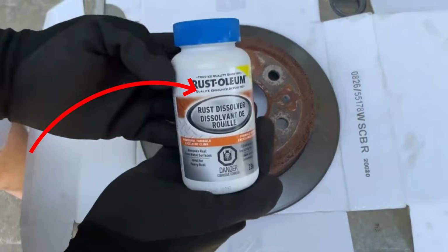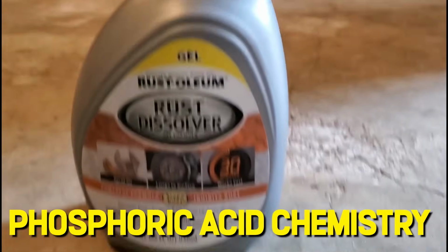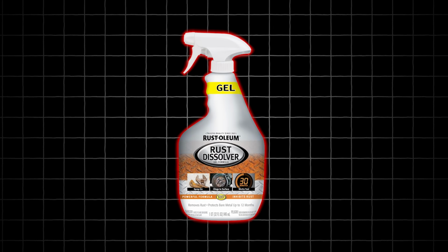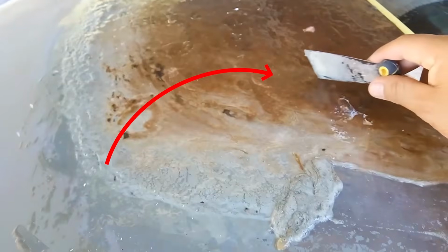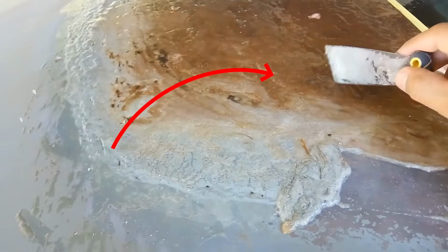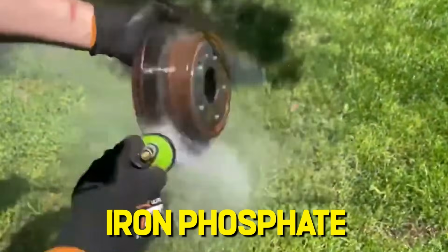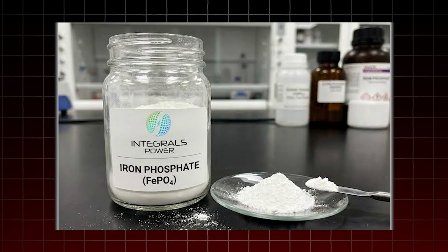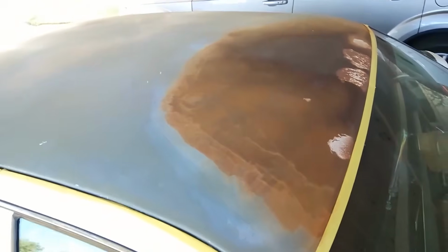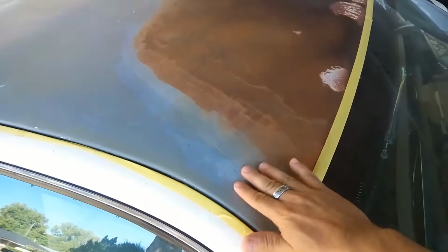Rust-Oleum Rust Dissolver Gel uses phosphoric acid chemistry rather than chelation. This is a meaningful difference from the previous products on this list. Phosphoric acid reacts chemically with iron oxide and converts it into iron-phosphate. Iron-phosphate is a more stable compound than iron oxide. It has a darker appearance, and it bonds to the base metal surface rather than sitting on top of it.